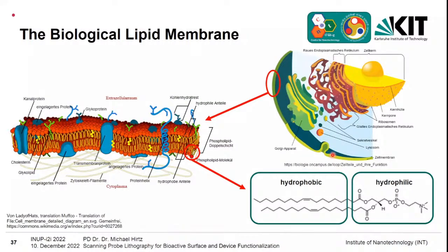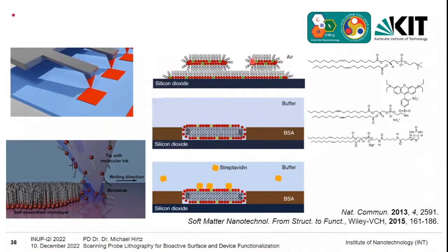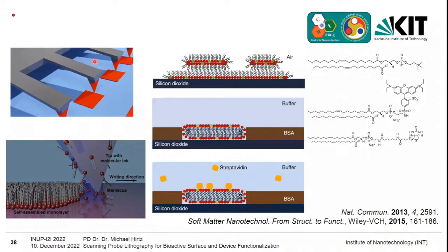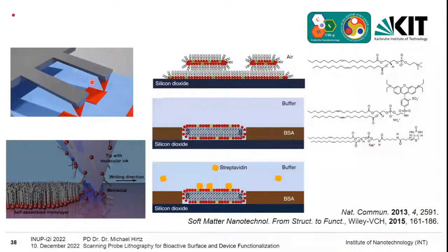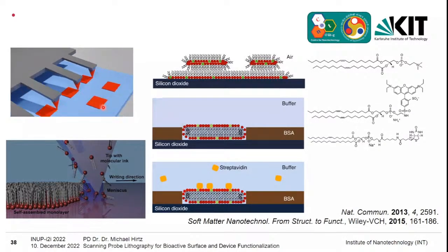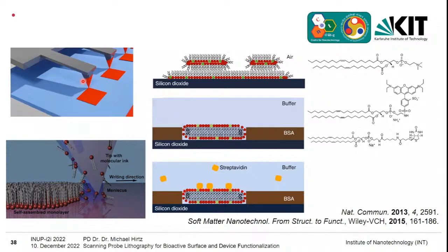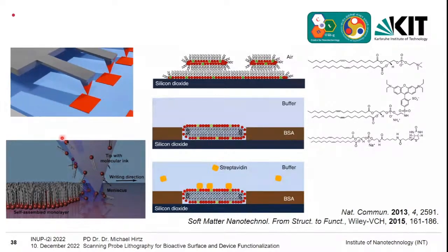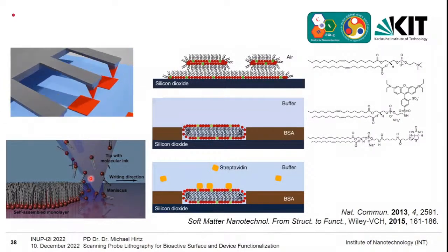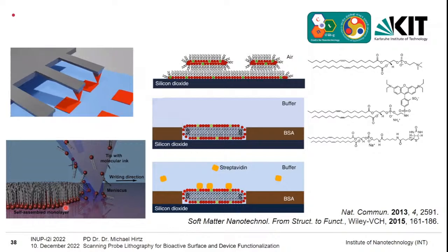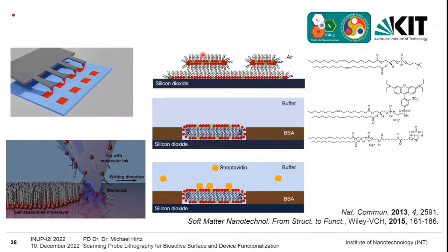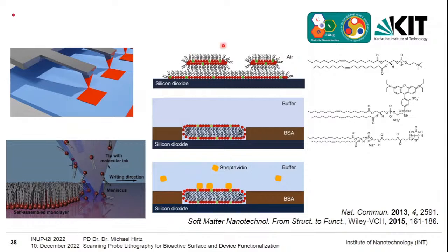So what we try with the DPN is then to make simpler versions of this for interfacing or also for sensing purposes. This is done more or less in this style. You can see here again a tip array writing, in this case, squares to the surface. And if you look at it in a molecular picture, it would work similarly, that you have the tips, the phospholipids, and they go from here to a monolayer on top. If you do that in air, then because of energetic reasons, you don't end up first with the biological membranes, but more with inverted membranes.